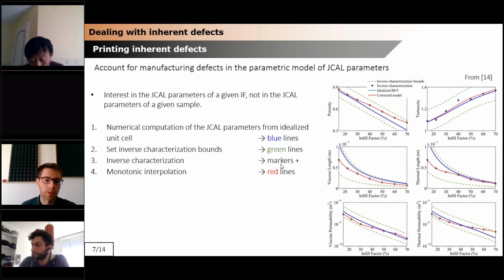Then we perform the inverse characterization on, I think, 8 homogeneous samples having different infill factor. And finally, we perform some monotonic interpolation of the data. In this way, we can obtain the variation of the intrinsic acoustic parameters of our microlattice in function of the infill factor.